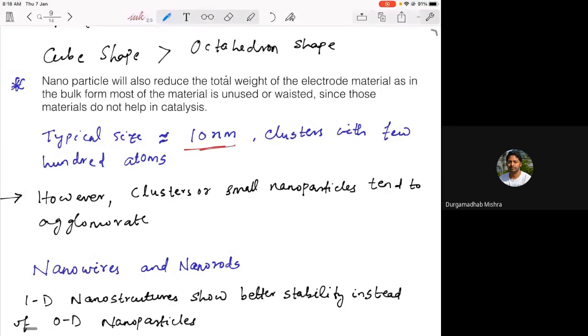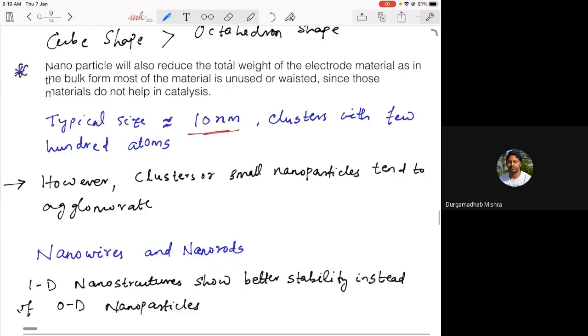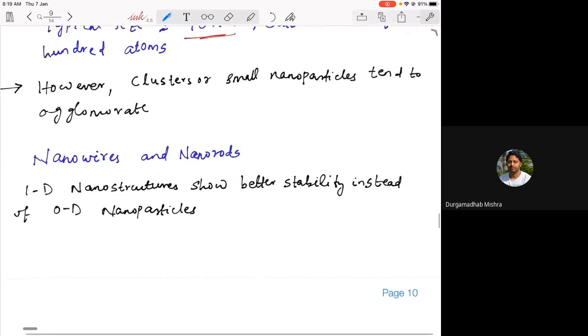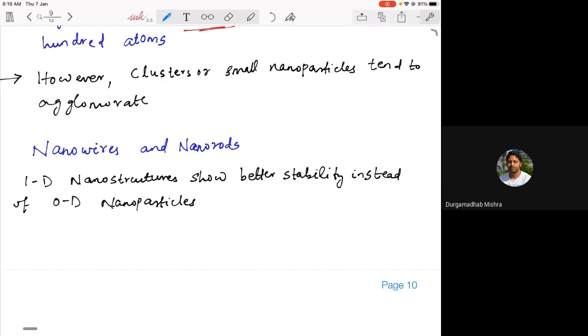They don't agglomerate so quickly, so you can put these nanowires or rods instead of nanoparticles, and you still can use the surface catalytic properties without agglomeration. In the beginning nanoparticles were used, and later on these nanowire or nanorod structures were used quite a lot. That means these 1D structures give better stability, with less agglomeration compared to your 0D structures.